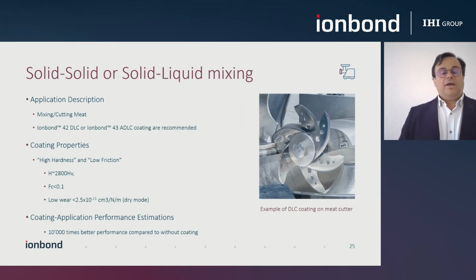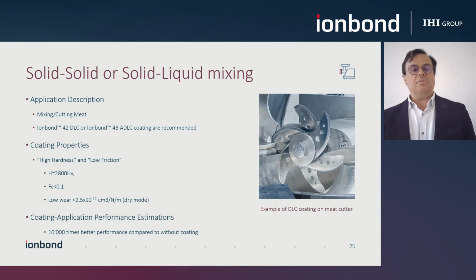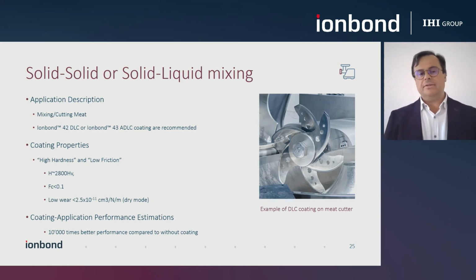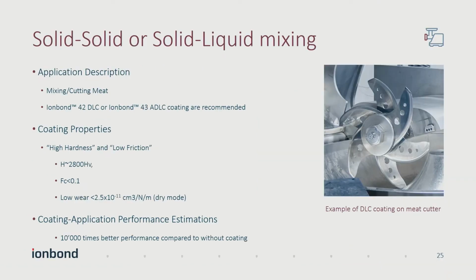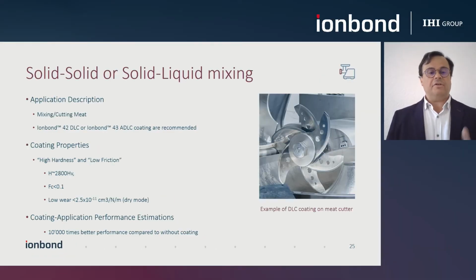With the next case, we start a number of slides about mixing. Here we are showing solid-liquid mixing. The example we are focusing on here is a meat cutter system. For this type of application, we also recommend the use of the diamond-like carbon coatings. Why? Because they have high hardness and low friction. And with these two components, as you have seen with Michael's graphs, you have very, very low wear. So with these attributes, we see a 4 order of magnitude improvement when you have the system coated versus uncoated.